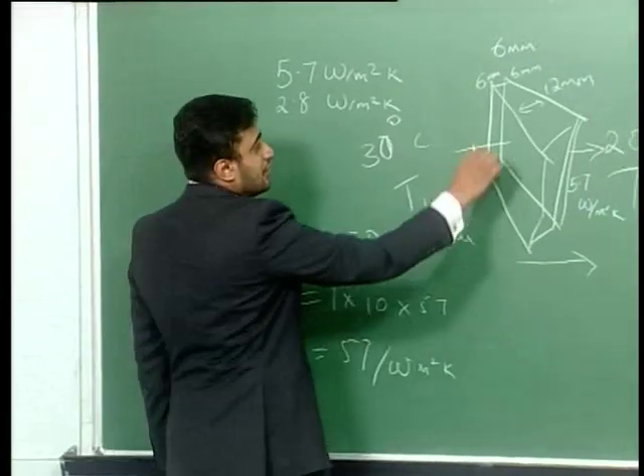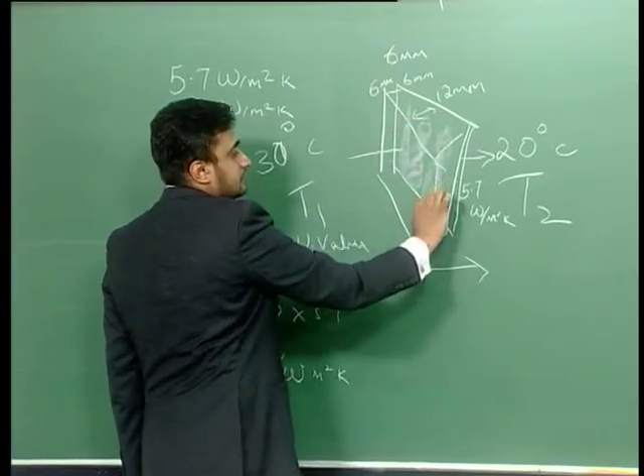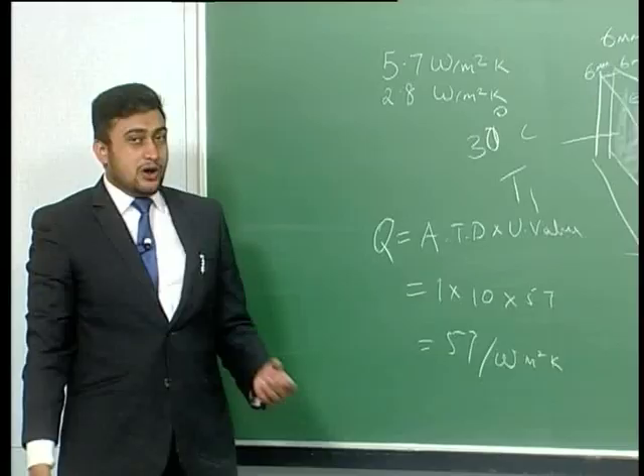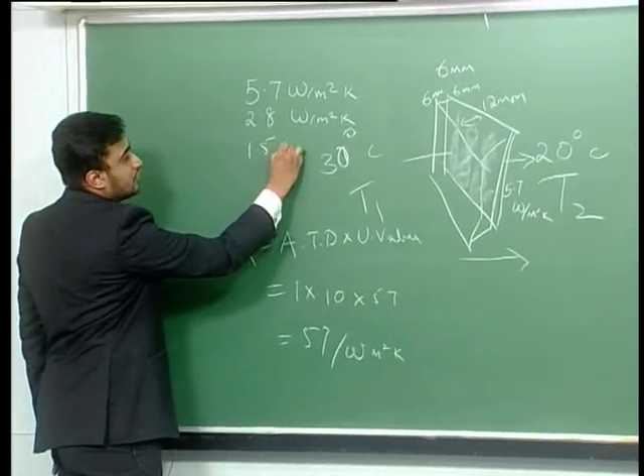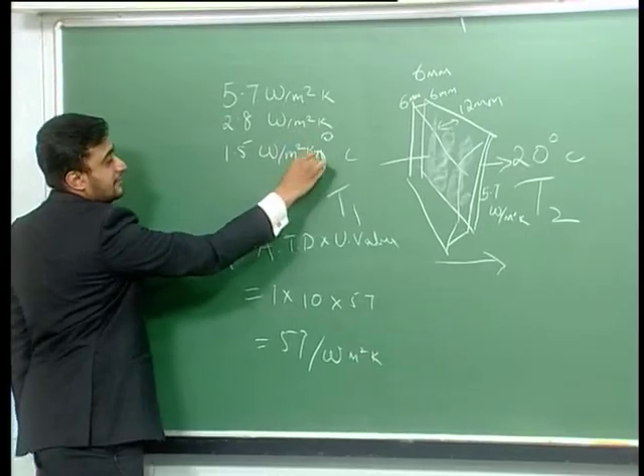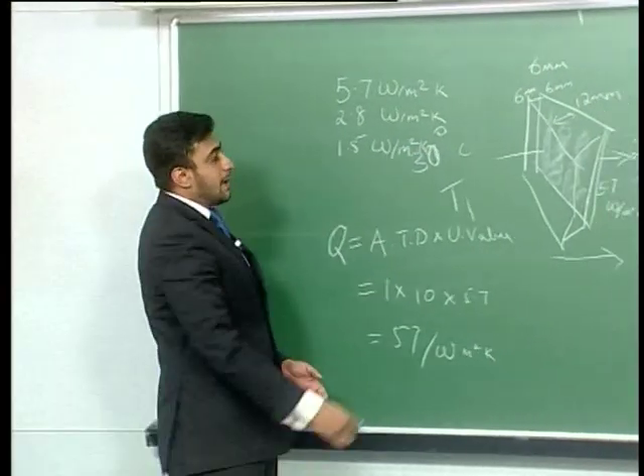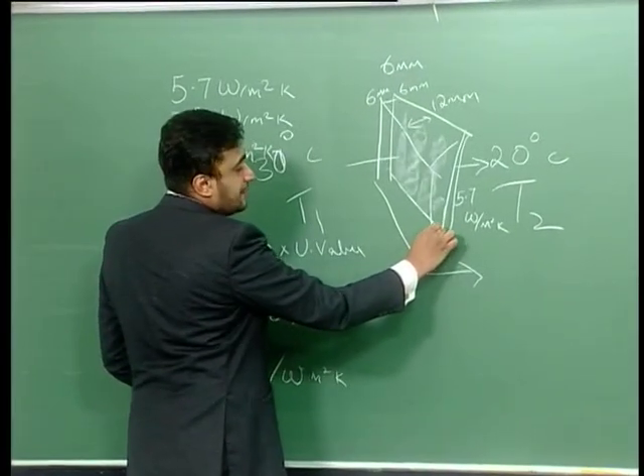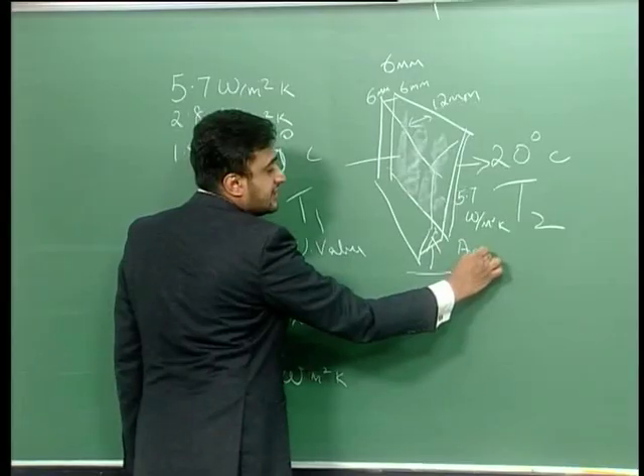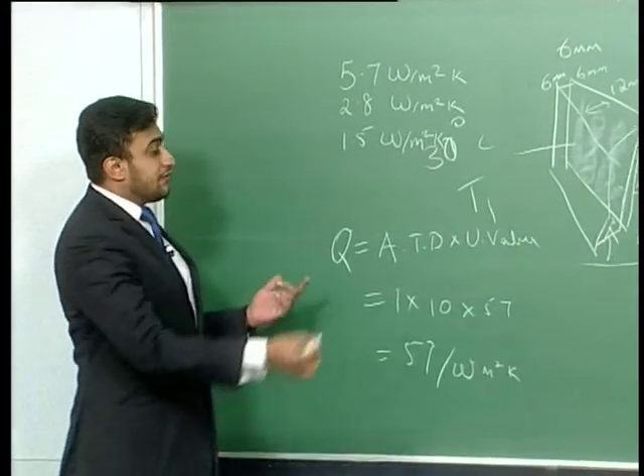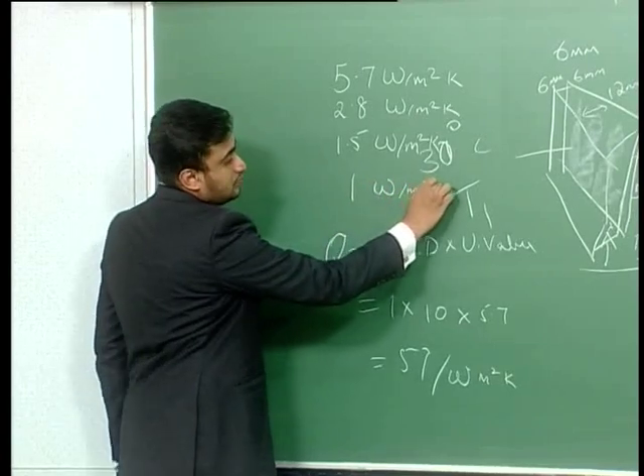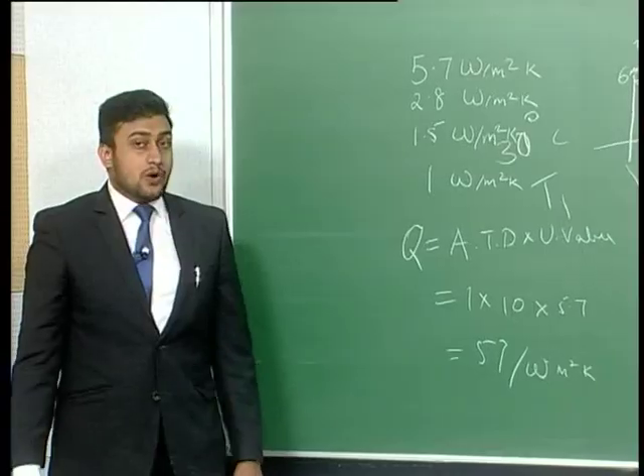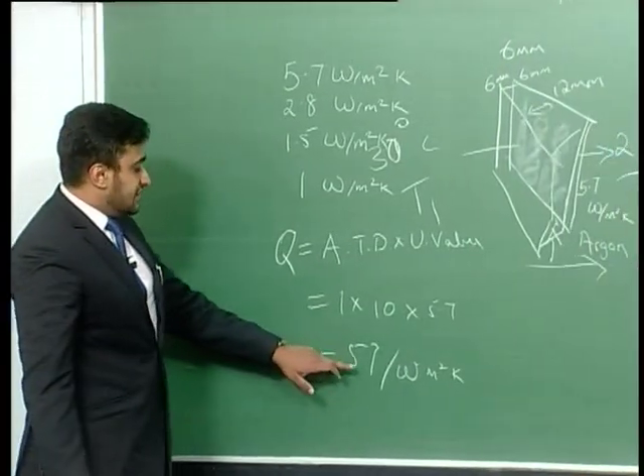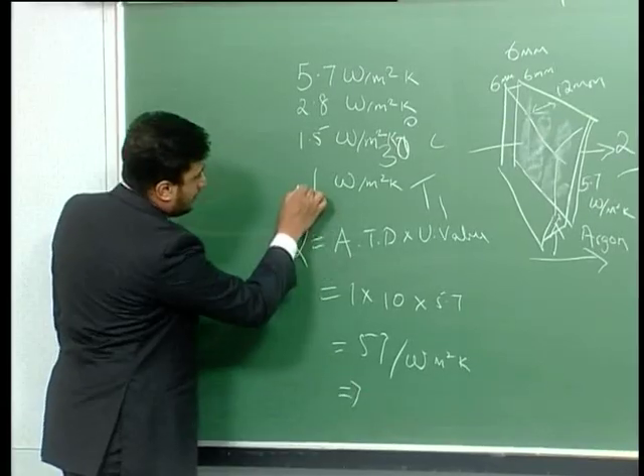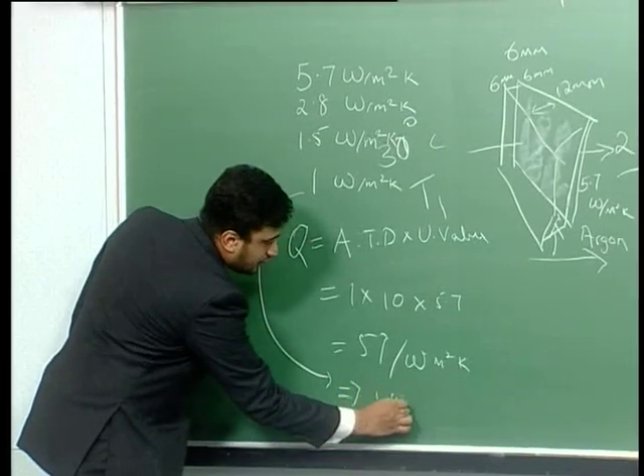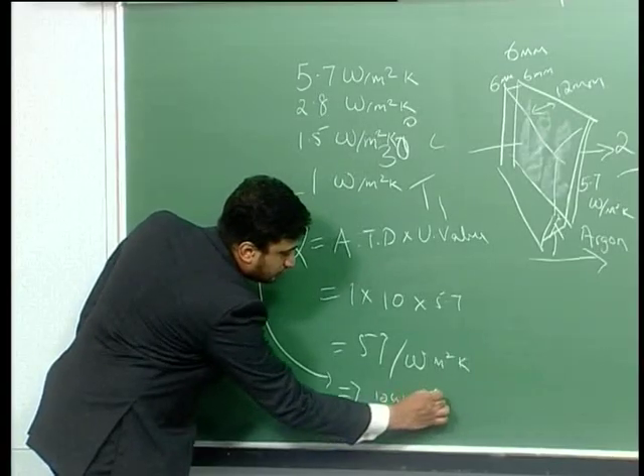This can be further improved by doing a coating on the glass. Once a coating is done, a low emissive coating, this can go down to 1.5 watts per meter square Kelvin. This can be further improved by replacing the air inside with an inert gas such as argon, which would further improve it to up to about 1 watt per meter square Kelvin. Now in this case the 57, if you had used this, would come down to 10 watts per meter square Kelvin.